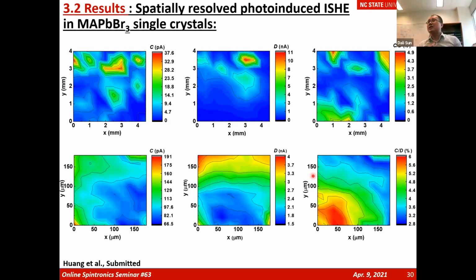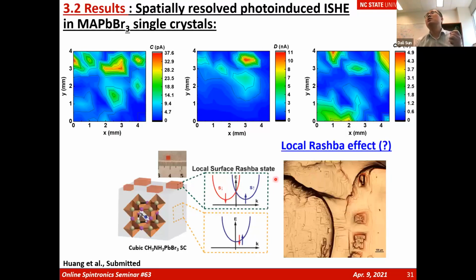So that gives us a hypothesis. Oh, that's the reason people didn't observe the Rashba effect in the single crystal, because this Rashba effect maybe is local. In the bulk crystal, it's cubic. Of course, there's no Rashba effect. On the interface, you have a surface state, you may be forming a Rashba state. However, our results show that the surface Rashba state only exists in certain spots that have a local symmetry breaking.